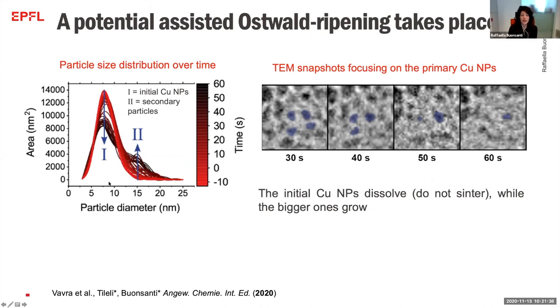Okay, so what Jan did was to start to analyze the particle size distribution over time. And what we saw is that the small particles shrink while bigger particles grow. But the small particles actually are not sintering and forming the big particles, they are actually dissolving in solution.